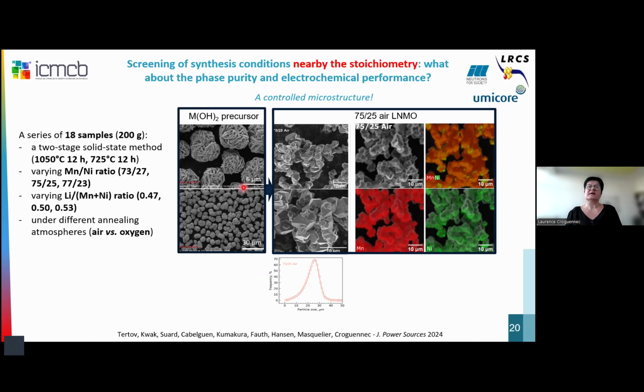And in fact, we made large batches of materials, 18 samples, that were prepared by Ilya at Umicore, starting with a metal hydroxide precursor from Umicore, you can see here. And in fact, in these synthesis conditions, at very high temperature for the first thermal treatment, in order to really promote growth of the particles, and so to promote low specific surface area, and thus, I would say, less interaction with the electrolyte and more stability versus degradation. And then we did a lower thermal treatment in order to try to promote the formation of the ordered phase, and that we did.